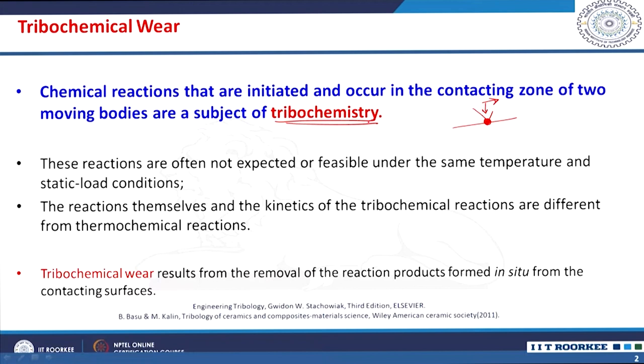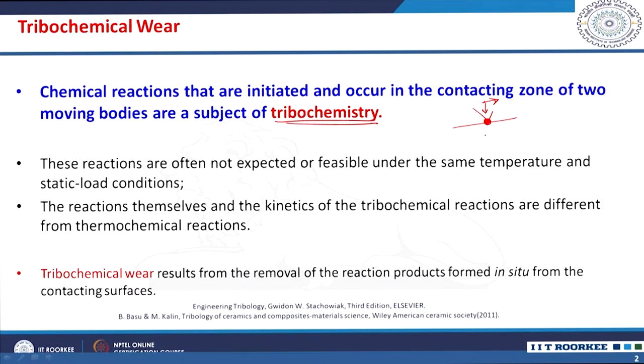These chemical reactions are often not expected or feasible under the same temperature and static loading condition, whereas under dynamic loading conditions, even lower temperatures are sufficient to trigger such reactions at the contacts because of the stimulated contacts and the high stress conditions. The kinetics of these tribochemical reactions are different from normally observed thermochemical reactions. So, the material removal due to the involvement of tribochemistry at the contact is called tribochemical wear. Tribochemical wear results from the removal of reaction products formed in situ from the contacting surfaces.